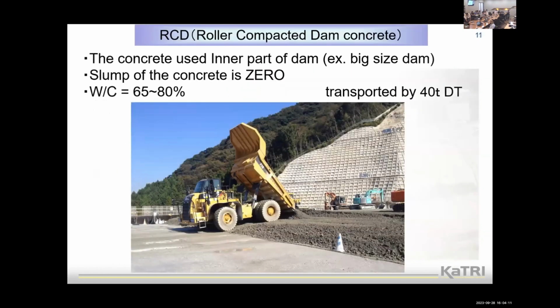So for example, for a big size dam, RCD, roller compacted dam concrete, is used also in Japan. When the height of the concrete dam is over 50 meters, we use the RCD concrete as the inner part of the dam concrete. The slump of the concrete is zero, and it's very hard. The water cement ratio, water binder ratio, is 65 to 80% almost, and the unit weight of binder is almost 120 kilograms per cubic meter. So the dam RCD concrete is very hard.